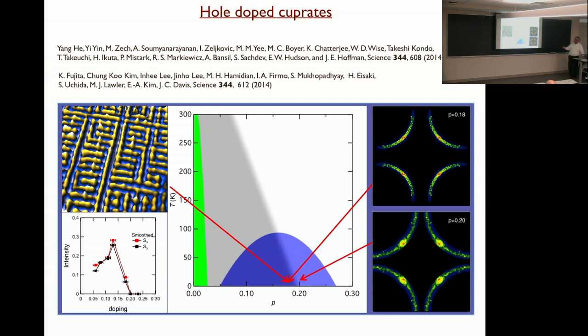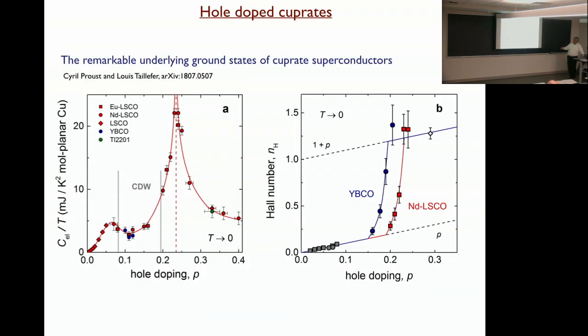I would say my answer is that it depends what you mean by responsible for. It's there, and it may well vanish at some kind of phase transition in the pure system. But the underlying theory is something quite different. It's not just given by a theory of charge density wave fluctuations, partly because these charge density waves are really tiny, especially when you get out here, whereas if you look here, this specific heat peak is quite well pronounced. And also the change in the Hall coefficient is quite dramatic.